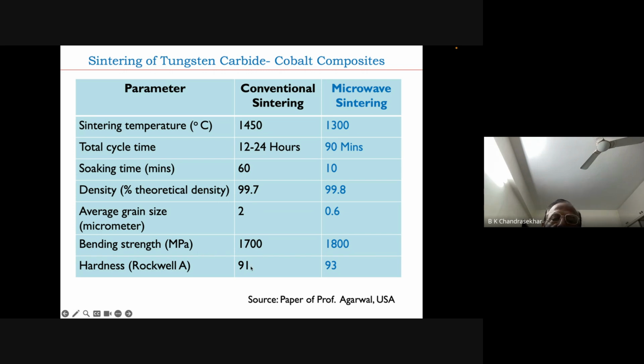Suppose I use microwave for sintering this material, then the sintering temperature can be brought down from 1450 degrees to 1300 degrees centigrade. A difference of 150 degrees centigrade.